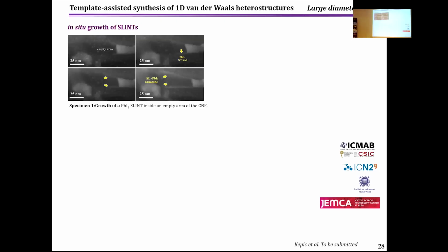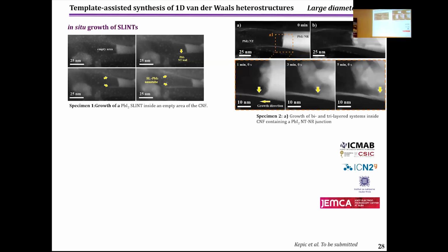So as I mentioned before, one of the main issues of the synthesis of this material is that we cannot control the growth, because we don't know the mechanisms of growth of this material inside. So we take advantage of some observations in TEM, as for example, the formation of a SLINT under the e-beam. We observed that single-layer nanotubes were formed. So we evaluate the effect of the electron beam on the formation of new nanostructures.